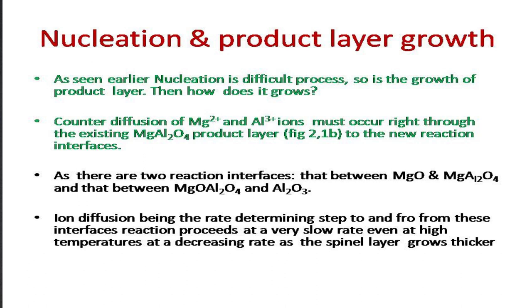Look at figure number 2, where I said earlier that on the right hand side the layer is larger, and on the left hand side the layer is smaller. Now what is happening is the interface between the reactants is shifting. One is moving towards the alumina side, one is moving towards the magnesium side. So these ions have to diffuse through these layers of the spinel in order to react at the interface. There are two reaction interfaces shown in the diagram, between spinel and the alumina and between spinel and the MgO.